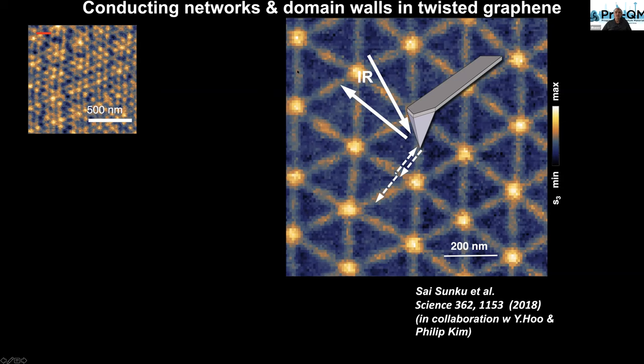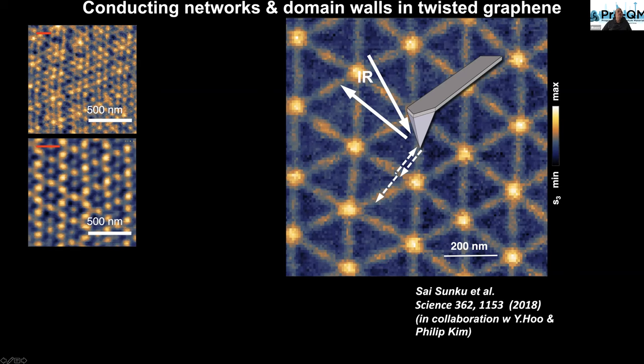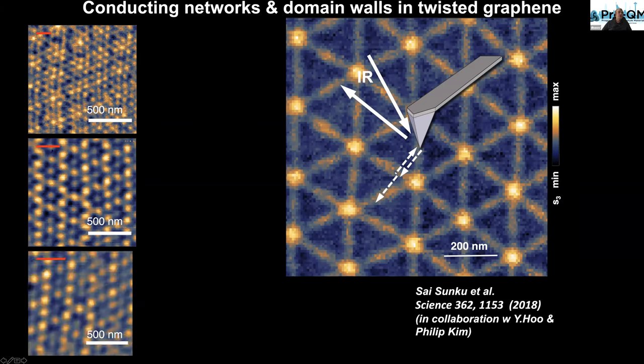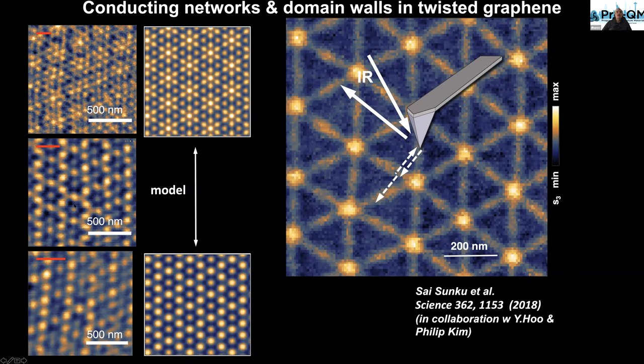They preserve the symmetry of this network, but they show quite complicated behavior. If we change the wavelength of this plasma polariton a little bit, the symmetry is still preserved, but some regions become darker, some brighter. It's a fairly complex evolution of this contrast. And this is work of Sai Sunku in our group at Columbia, together with my collaborator in all of these projects, Michael Fogler at UCSD. We were able to reproduce all aspects of this complex evolution of standing wave patterns.